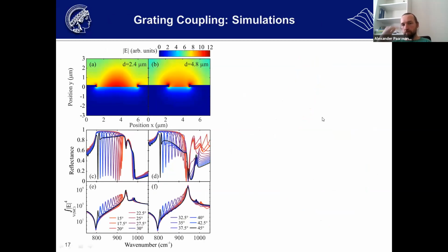In order to wrap our head around this, or try to understand why this is happening, we did some simulations. Simulations don't always tell you why things are happening, and in this case it's not necessarily the case either. But at least we can recover the same kind of behavior. So we set it up in the same geometry as our samples. You see that the reflectivity looks perfect, with nicely dispersed counter-propagating modes. There's a slightly different behavior for the wider gold bars.